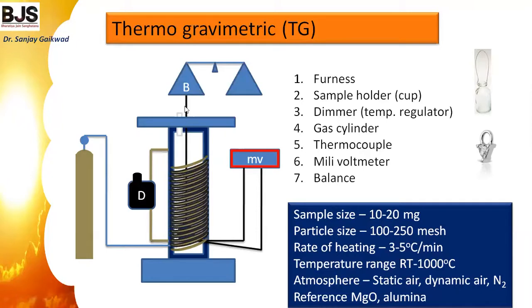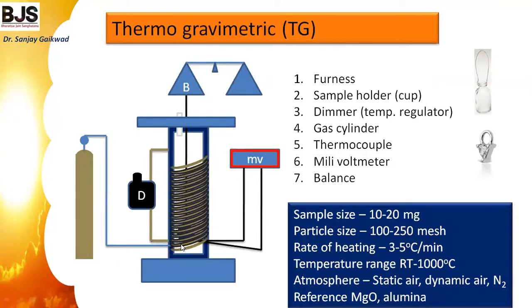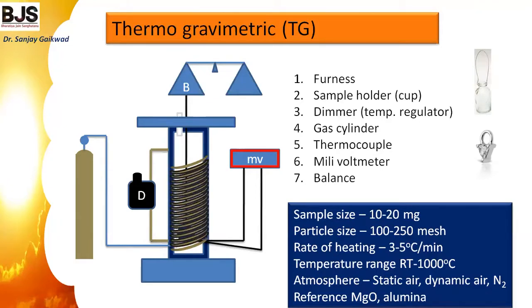The sample holder is connected to the balance, and we measure the change in weight as a function of temperature. Temperature is measured in millivolts, increasing at a constant rate using the dimmer, which steadily raises the furnace temperature in either nitrogen or oxygen atmosphere. The sample is kept in the holder — quartz or platinum — and its initial weight is set as zero on the balance. A small quantity of sample, 10 to 20 milligrams, is placed in the disc-shaped crucible.